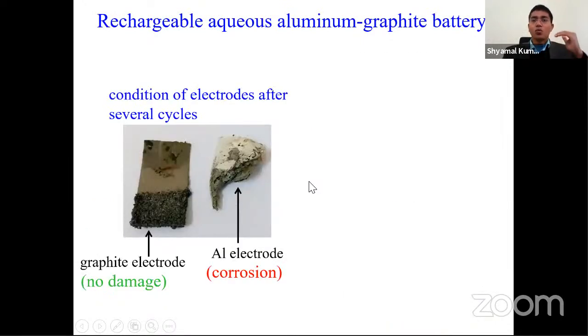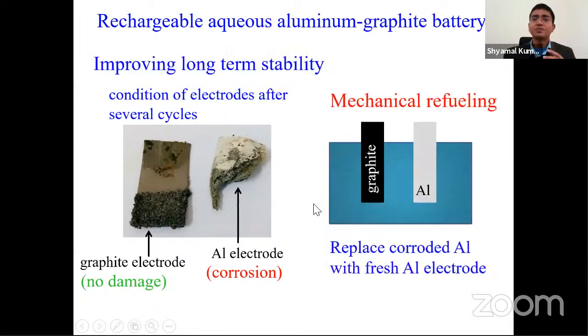One of the issues that we faced during this work is that when we run the battery for several cycles, for several hours, we see severe corrosion of the aluminum electrode. On the other hand, on the graphite electrode, we see no kind of damage. So we proposed a mechanical refueling model to improve the long-term stability. Let us say this is your aluminum graphite cell. We have one piece of graphite, one piece of aluminum.